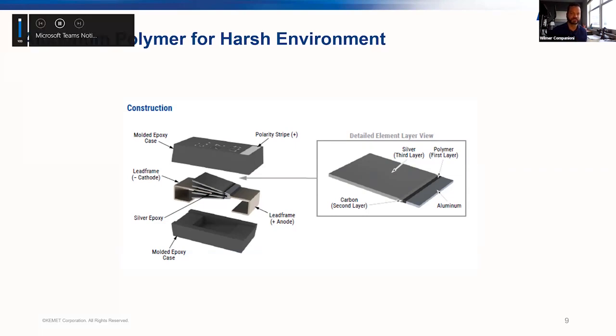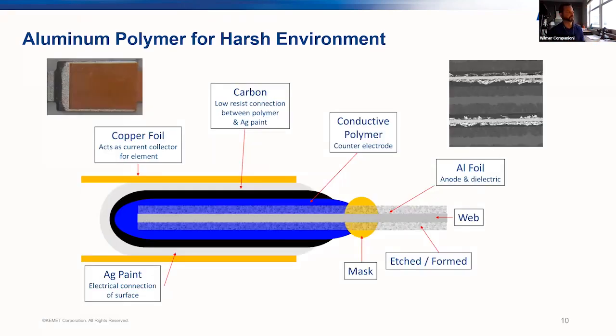So in the case of tantalum polymer, you have a slug of sintered tantalum powder with a dielectric layer grown on it. In this case, it's actually more like little sheets, almost imagine little sandwiches of aluminum all stacked inside of an epoxy casing. So let's take a look inside of it and see what that looks like.